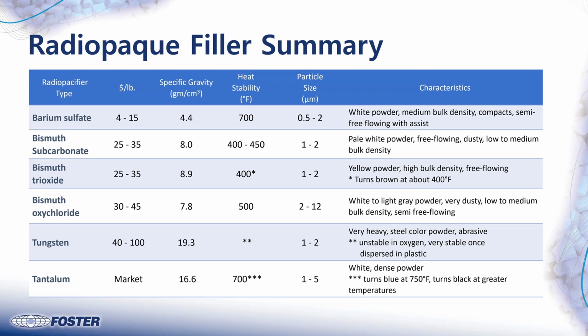It's not crystal clear, but you can see through it, and sometimes in a catheter application you do want to see the optical translucence. There are formulations in polyurethanes. The radiopacity is not strong. It's similar to barium sulfate, and I would say it's similar to a barium sulfate with 20% loading. But we do have a lot of customers that call that out. And then of course almost everything we do is customized, so we can reinforce a radiopaque compound. We can add lubricants, pigments, and so forth. We are limited on colors once you put radiopaque fillers in the product. Barium gives you the widest range of colors, but we can't color it.